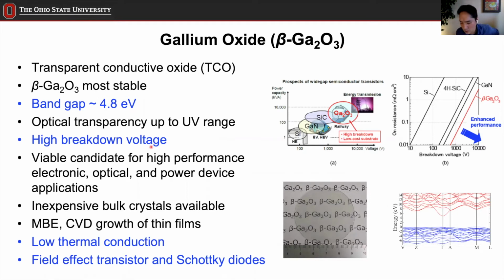And therefore, it becomes a very good candidate for high performance power device application material. Okay. One very important technical advantage is that gallium oxide is not only for thin films. If you look at gallium nitride, usually they are thin films, right? And then the substrate has to be something else, because if you try to make bulk gallium nitride, that bulk growth is very difficult and also very expensive, which is not the case in gallium oxide. Gallium oxide can be easily grown into bulk crystals, and that's pretty cheap. Not as cheap as sapphire, for example, but it's still pretty cheap.